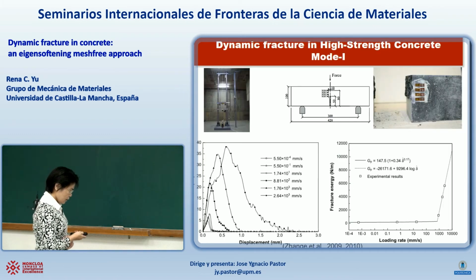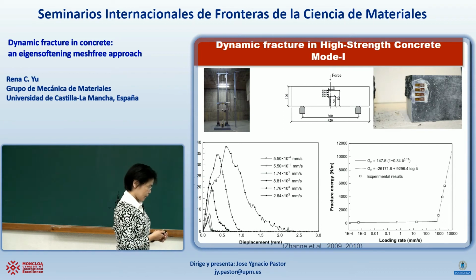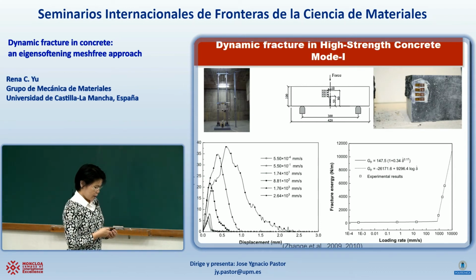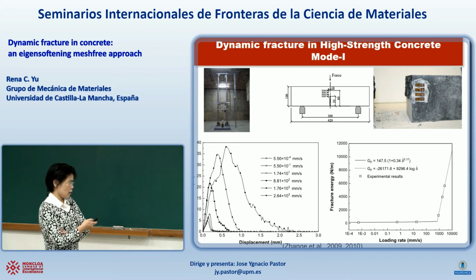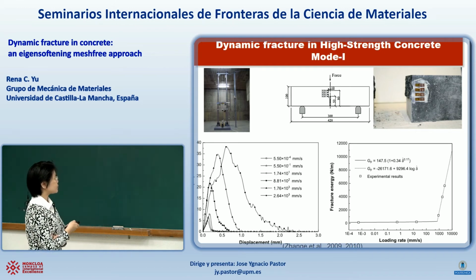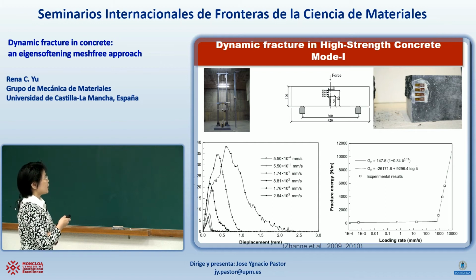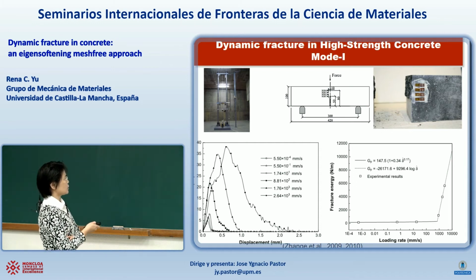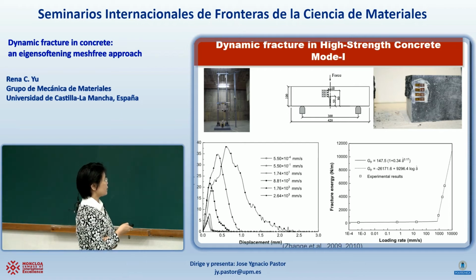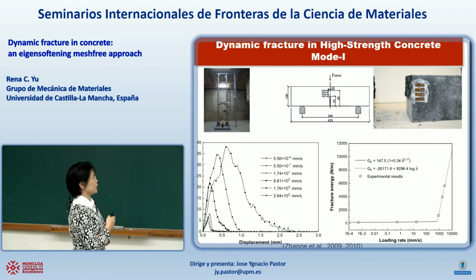Okay. So once we have established the meshfree framework for fracture, remember we also defined the softening approach to fracture. We would like to model some dynamic fracture in high-strength concrete. Actually, this was one of the broken pieces of a beam. So what we see here is a beam where the span is 300 millimeters and the total length is 420 millimeters. It has a notch to half of its height. The height is 100, and also the width is 100 millimeters.